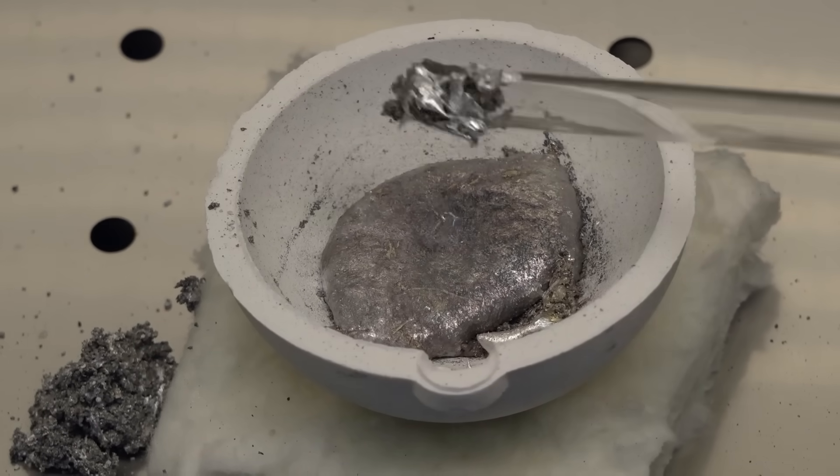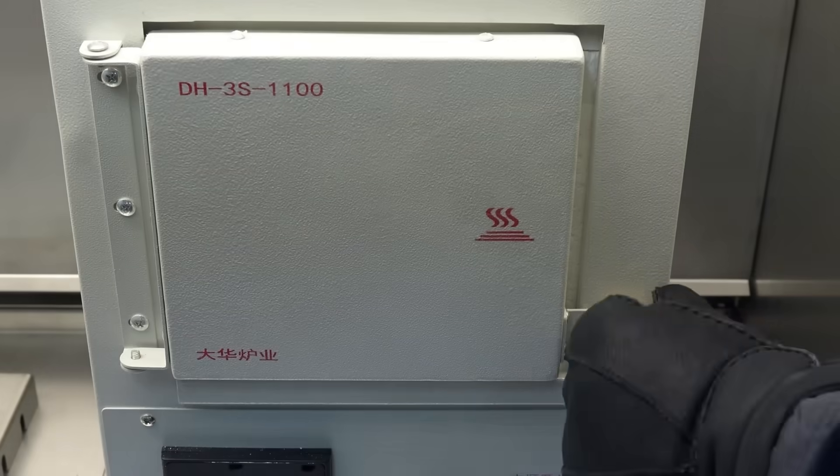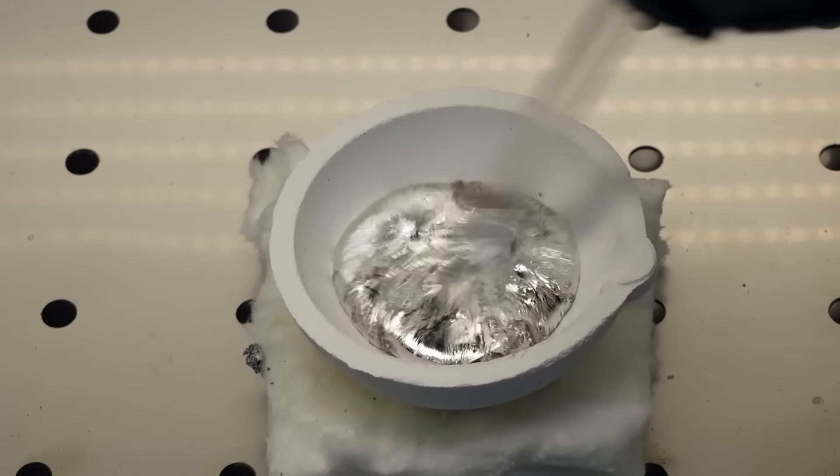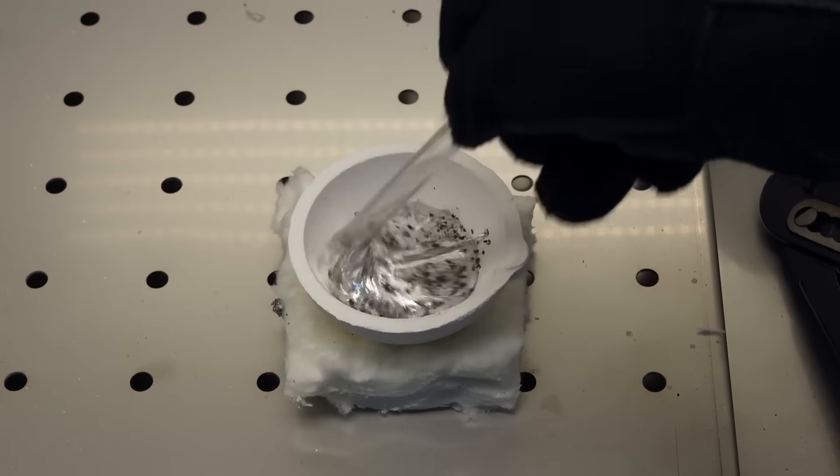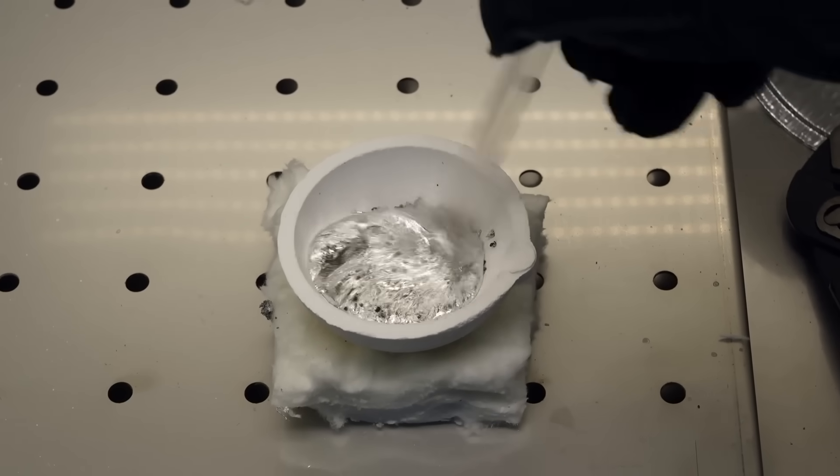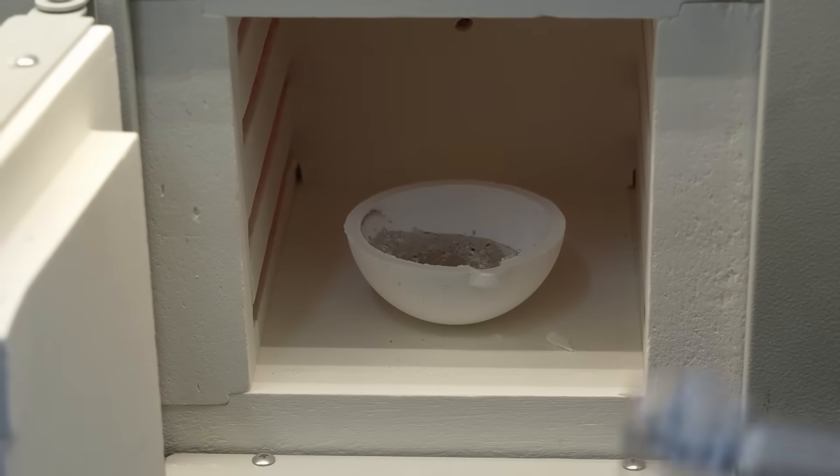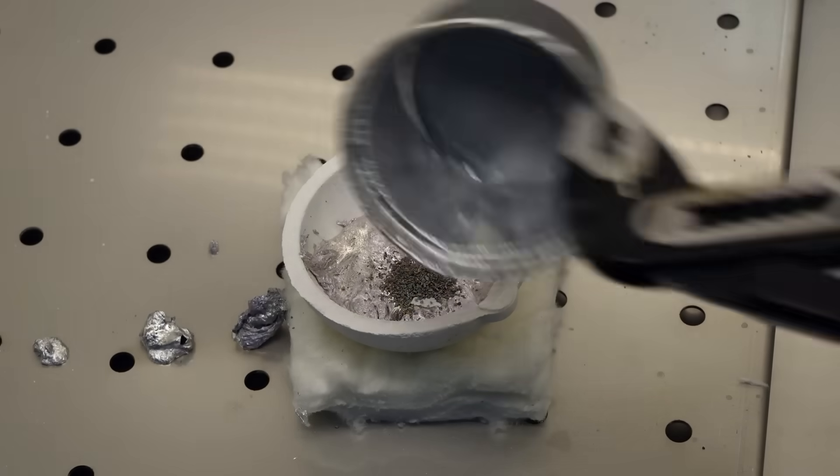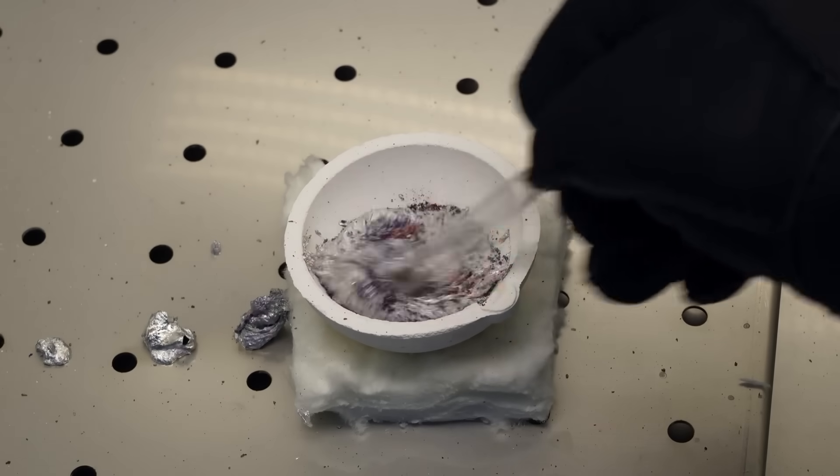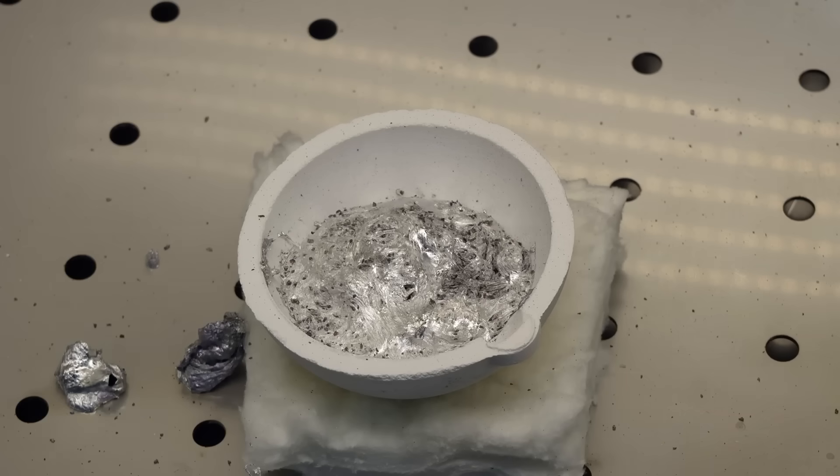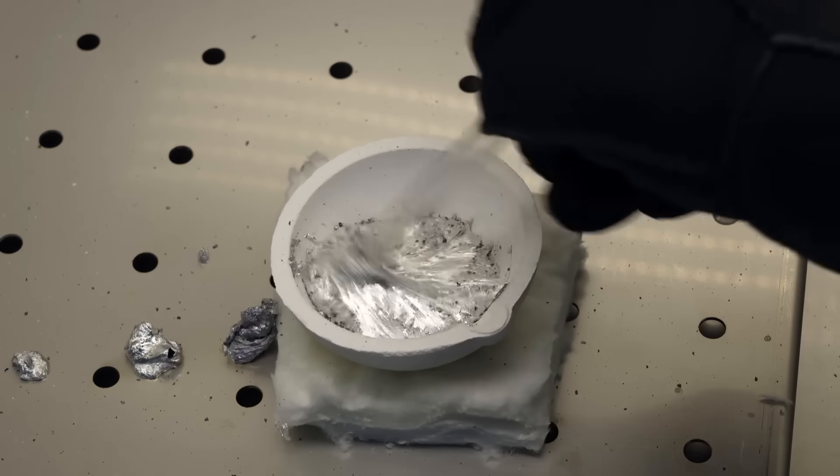Unlike sodium hydride, which can spontaneously ignite on a wet surface, titanium hydride is more stable and can be stored for a very long time without decomposing. Nevertheless, after, in my opinion, the aluminum has melted with the calcium, I take the crucible out of the furnace and quickly, while the alloy is still hot, add the titanium hydride to it.